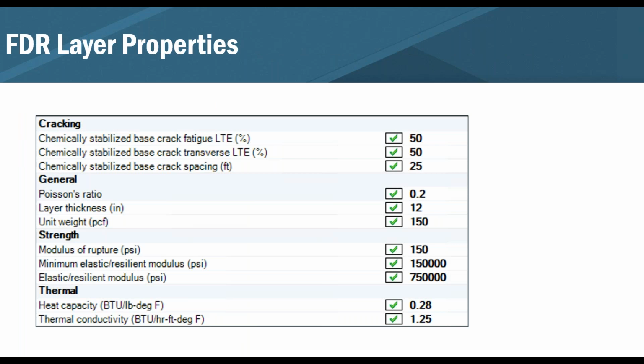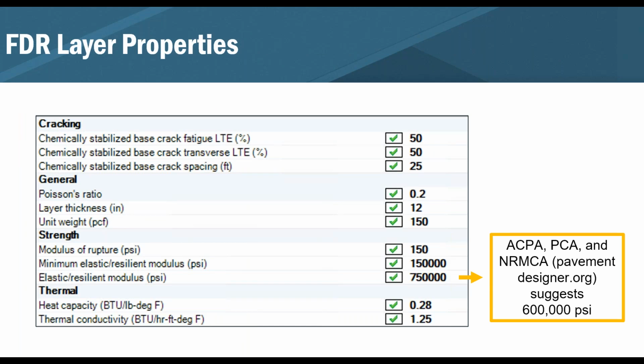For the FDR layer, it went through looking at different inputs, and pretty much the DOT uses an elastic resilient modulus of about 750 KSI. And this is again just straight from what Virginia does. But the ACPA, the PCA, the National Ready Mix, they actually have a little program, pavementdesigner.org, where you can get it. And they actually suggest 600 KSI. So for anybody not really knowing how to characterize that, certainly 600 KSI is a good place to start for those values.